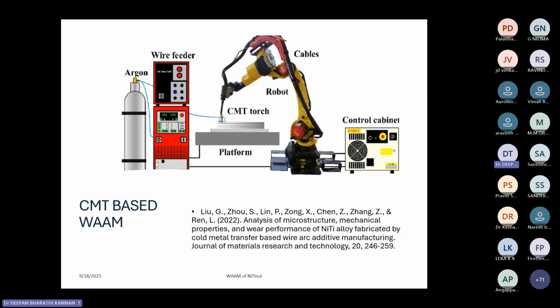Most of the work done on nitinol shape memory alloy is done with respect to CMT, cold metal transfer arc welding, where we have a special type of setup to retract the wire front and back, which helps us reduce the heat input, and also helps us minimize the spatter. So people are also exploring this to a larger extent with respect to nitinol shape memory alloy.